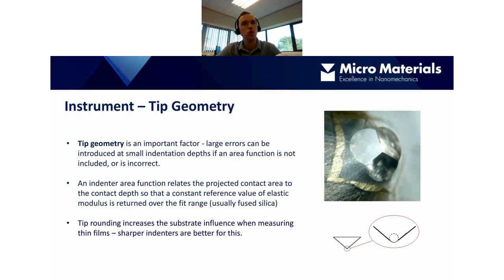So tip geometry, which we briefly mentioned before: once we get down to the very tip of the Berkovich indenter, it's often more like a sphere with, as we said, a radius of around 50 to 100 nanometers. So it's important that when we analyze indentation data, we include what's called an area function. This essentially characterizes the geometry of the tip and relates the contact depth to the contact area. This is particularly important if we're performing indentations that are very shallow, where the volume of the indentation is predominantly this spherical tip area. Because if we don't include an area function, then we can get a significant overestimate of the hardness and modulus values when we're performing these very shallow indentations.